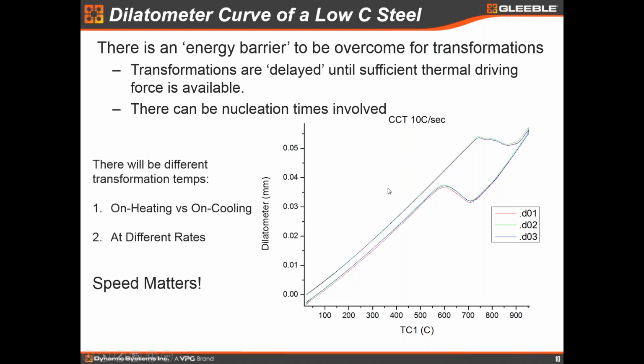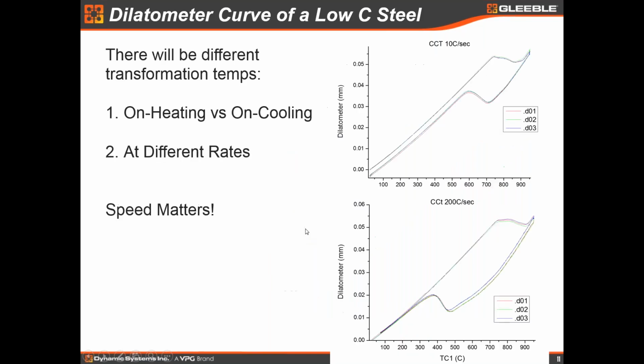One of the other things that's important to mention, and one of the big benefits that Gleeble has when doing dilatometry, is that speed matters. I've spent some time explaining why we can get good measurements at very fast heating and cooling rates in a Gleeble, where that may be more difficult to get in some other machines. So the faster the cooling and heating rates are, the more these temperatures will shift based on the heating and cooling rate, and therefore the more that Gleeble technology becomes an important factor in being able to gather accurate data here.